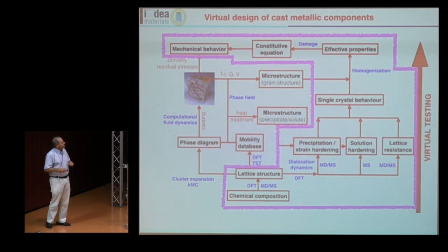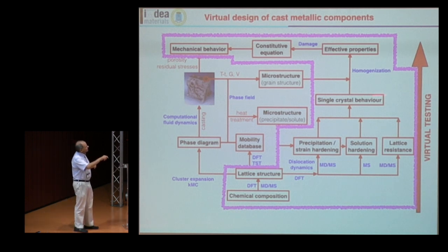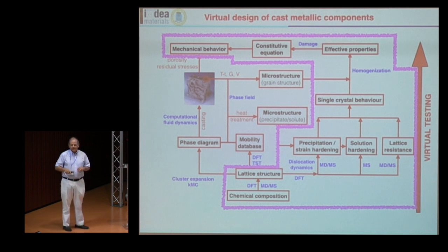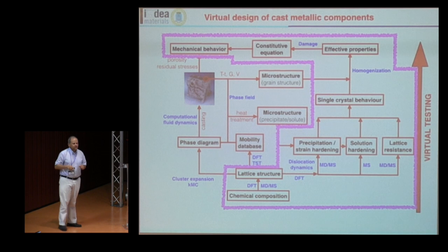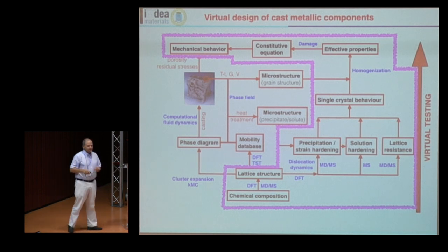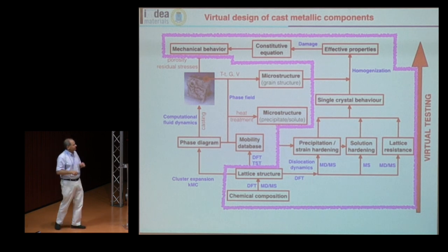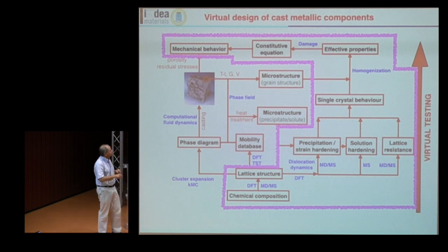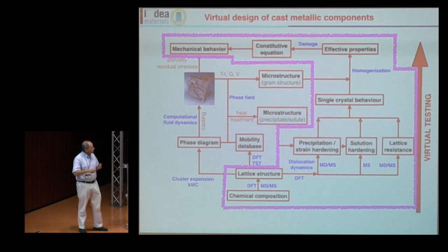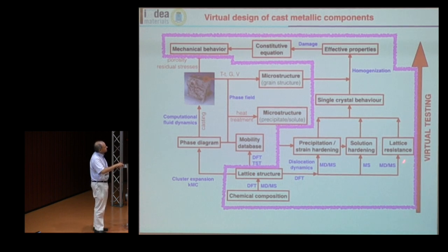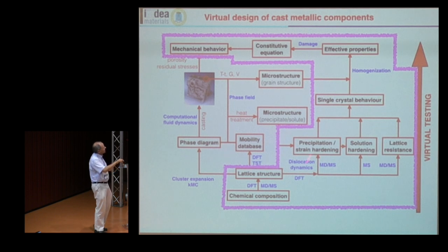The second part is what I call virtual testing. If you know the single crystal behavior and have a mechanical constitutive law plus the crystalline structure, you can do computational homogenization, get the effective properties, add a damage model, and get the constitutive equation and mechanical behavior. Getting the constitutive equation of the single crystal is complicated because there are a number of hardening mechanisms: lattice resistance (anisotropic, especially for HCP materials), solution hardening, precipitation hardening, and strain hardening. Starting from the chemical composition and lattice structure, and using DFT and dislocation dynamics, you can obtain the lattice resistance, solution hardening, and account for all these contributions.